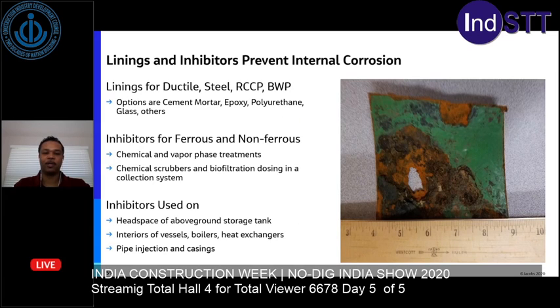Some lining options for ductile iron, steel, RCCP, and BWP pipe have traditionally been cement mortars, epoxies, polyurethanes, and glass linings. You can use inhibitors for both ferrous and non-ferrous materials. Some example inhibitor applications have been on the headspace of above ground storage tanks, the interiors of vessels, boilers, and heat exchangers, also during pipe injection, and also with casings, the interstitial space of those casings as well. Next slide.